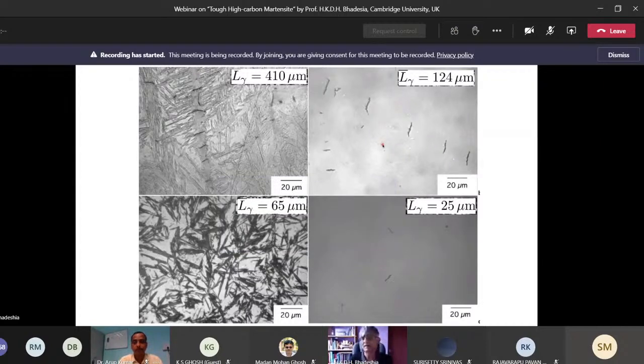There's one more thing I want you to notice, and that is in order to give you an explanation for why austenite grain size and the martensite plate length matters in terms of cracking. If you look at these cracks, they are kind of periodic, all right? So there is roughly the same spacing between these cracks. So on experiencing a stress, the plate has broken up into segments which are approximately equal in length. So if I now make my austenite grain size much smaller than the distance between cracks, then I should eliminate the cracking.